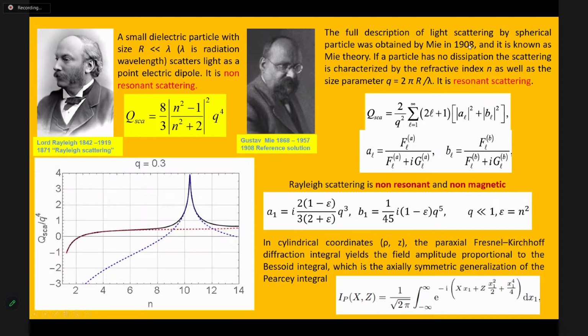In 1908, Mie published his paper about Mie theory. He was not the first; at least 7 people before Mie obtained the same formulas, but he made a physical discovery. He paid attention that scattering may have resonant nature, as shown here. If we divide the scattering efficiency by the size parameter to the power 4, then it is a function of the refractive index only. So for Rayleigh scattering, it tends to some constant, like 8/3. But in the case of Mie scattering, we can see huge resonance. It depends on the refractive index and the size parameter.